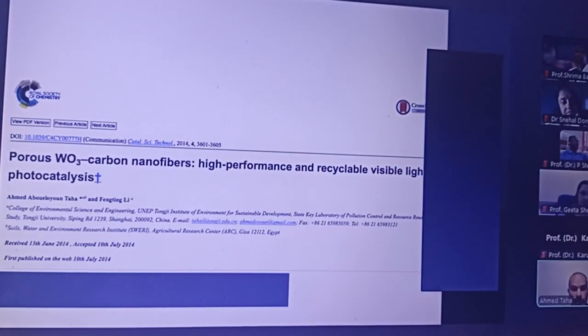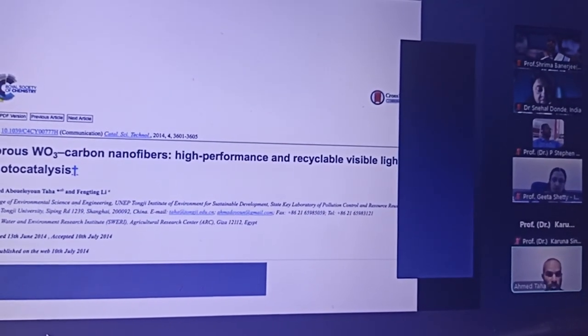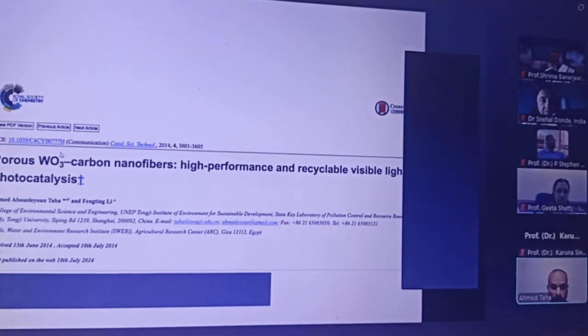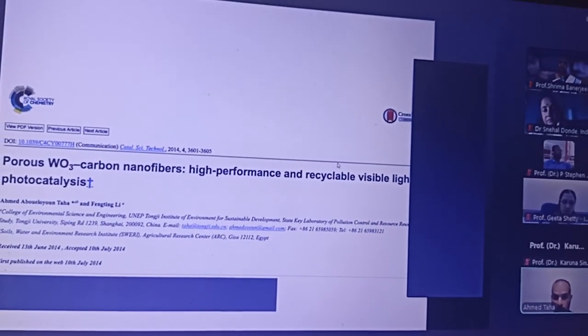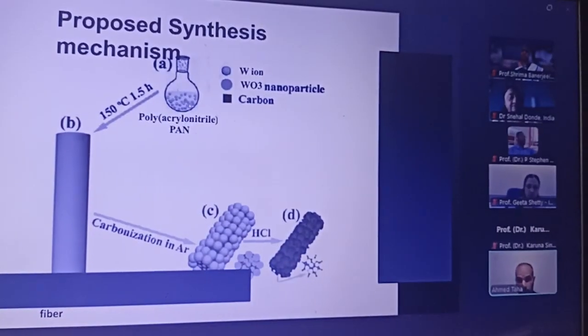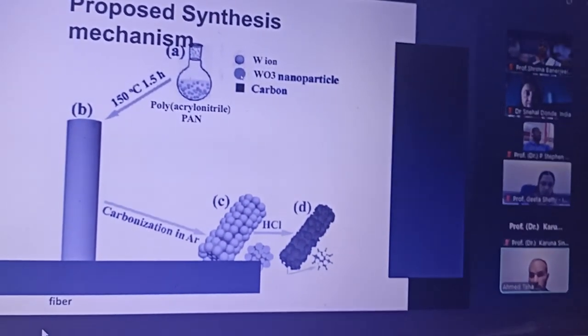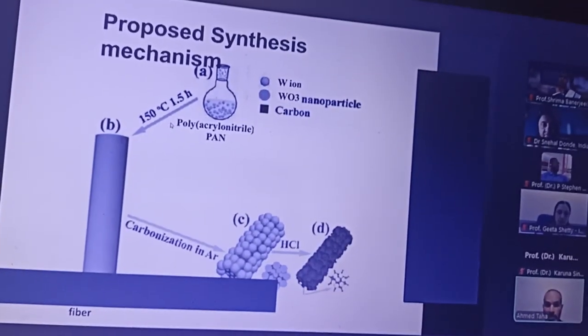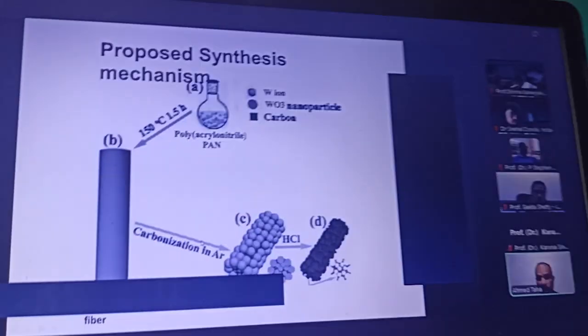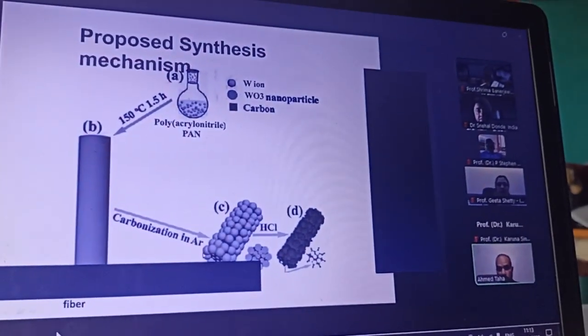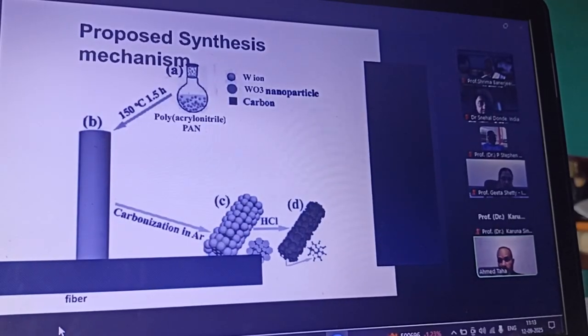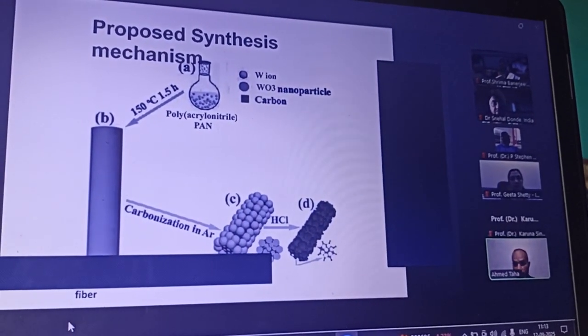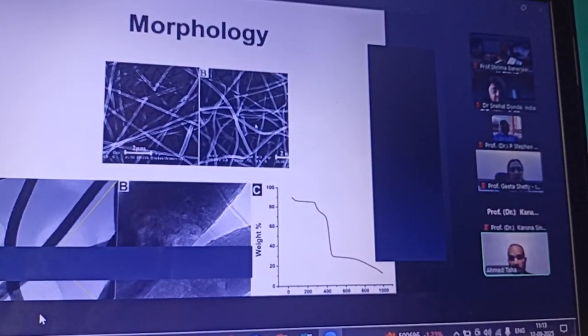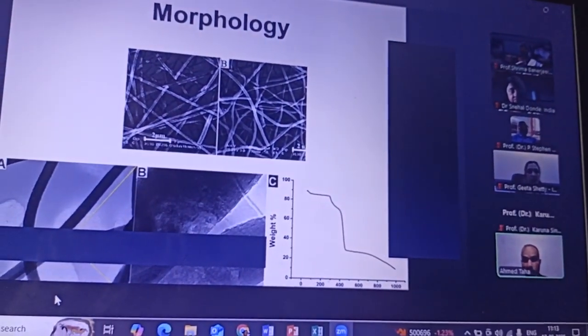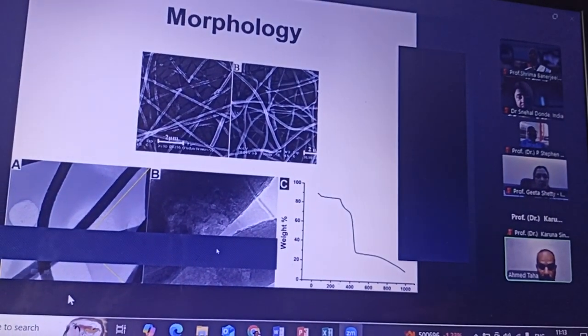So we have done some research on this. We used carbon nanofiber with one of the semiconductors, tungsten oxide, and visible light. We mixed the precursors, the polymer, with the semiconductor salt, and then went through electrospinning again to produce a fiber. We took this fiber and did thermal treatment to convert the polymer into carbon material in an inert atmosphere. So we have this material by the end. This is a fiber, but it is actually a carbon fiber. And if you look at the surface,